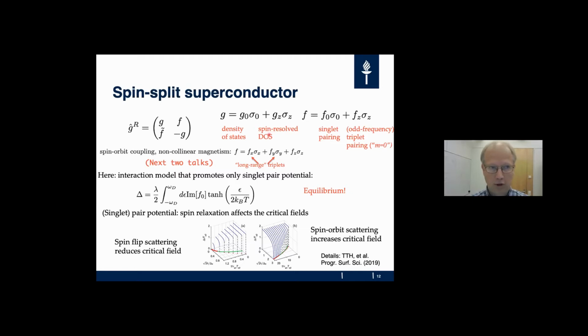So both G and F get this non-trivial spin dependence. The G part describes the spin-resolved density of states, and the F part - F0 is the singlet pairing amplitude, and then Fz is actually a triplet pairing amplitude.